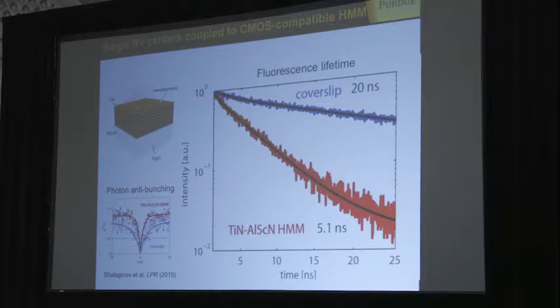And sure enough, when you place nanodiamond with NV centers, we choose the size so that on average you have one single NV center in nanodiamond. You see that significant increase in the rate with which these photons are emitted as compared to just a glass substrate. And to prove that we are dealing with single photons, we, of course, as everybody does, look at this G2 correlation function, and indeed it shows this large dip way below 0.5. This is just one single example of how this metamaterial, based on new plasmonic materials, which are CMOS compatible and really nice, could be used for quantum photonics applications.